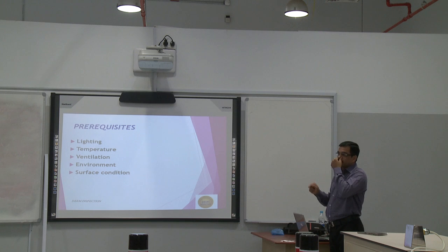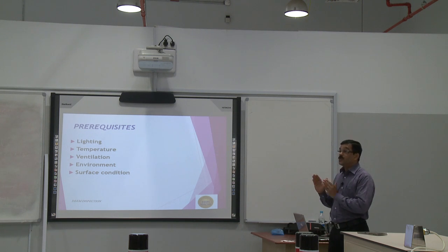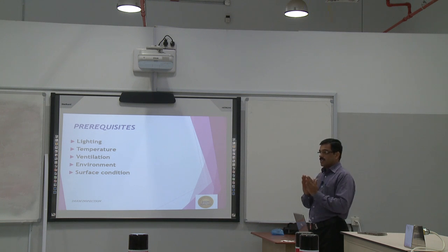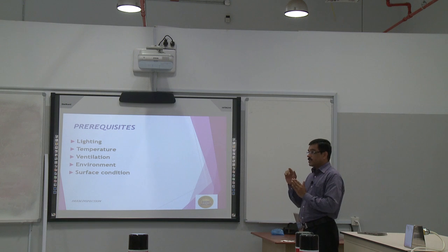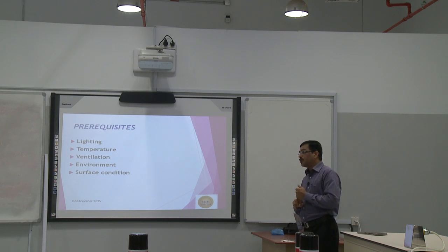But penetrant testing we can do from 16 to 52 degrees Celsius, with a minimum and a maximum.